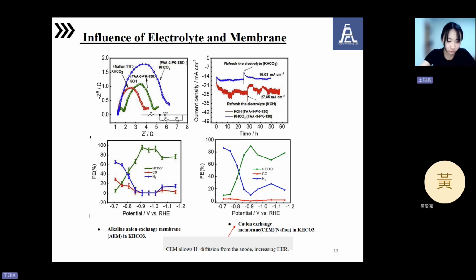In the CEM case, hydrogen becomes dominant, especially at more negative potentials. The reason is that CEM allows hydrogen ions to migrate from the anode to the cathode, which promotes HER and reduces the selectivity toward formate. In contrast, the AEM blocks hydrogen ion crossover, suppressing HER, and helps maintain a high selectivity for formate production. So overall, this clearly demonstrates that the choice of electrolyte and membrane is just as important as the catalyst itself when designing an efficient CO2R system.